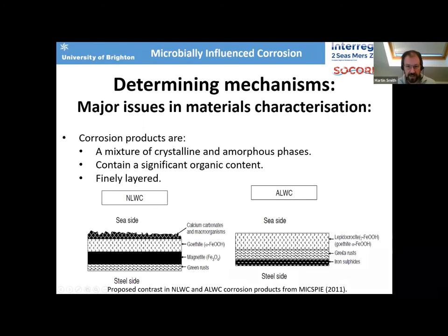Green rusts are essentially a range of mixed iron oxidation state, either carbonate or sulfate minerals. And we're getting iron sulfides against the steel surface. So we need to test that mineralogical structure to the corrosion to work towards understanding the determining mechanisms. And then we can hopefully build towards understanding what's going on and doing something about it.